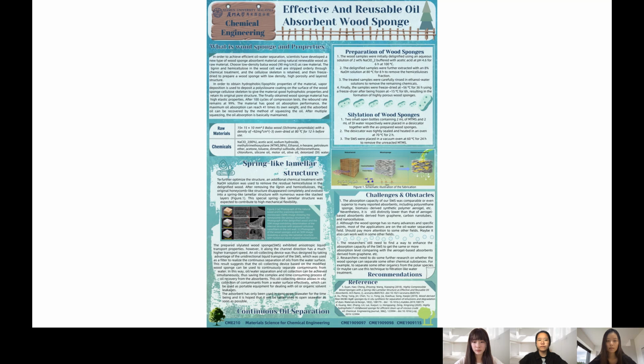Now I will show the specific structure of the wood material. We can see this 9x9 photos. It shows the differences of the three stages of the development of the wood material. We can see the first row in the figure. It shows the natural wood, the SEM image of the detailed structure. With the development of the material improvement, we have the delignified wood, as it shows in the second row. The structure is similar to the honeycomb structure, but it shows more layers.